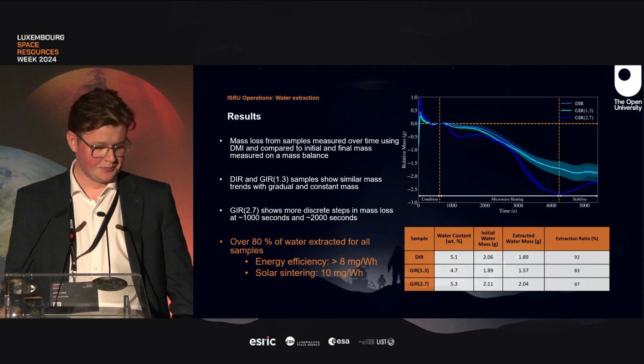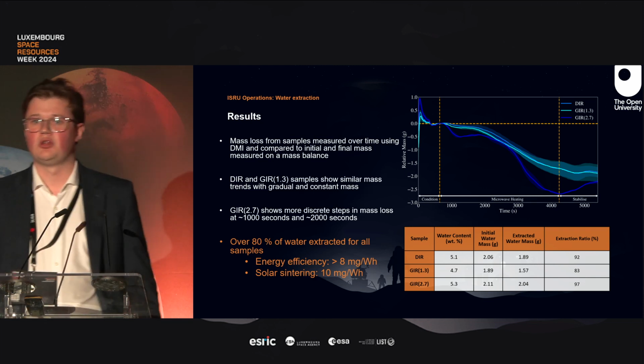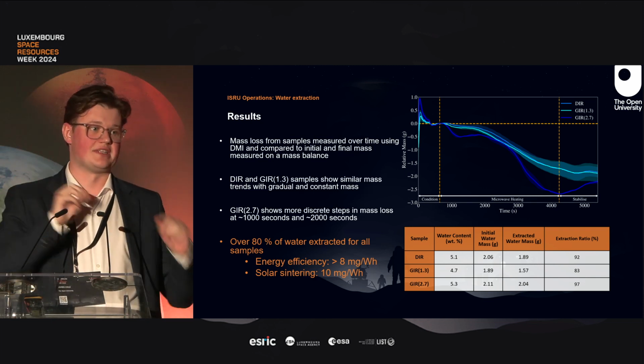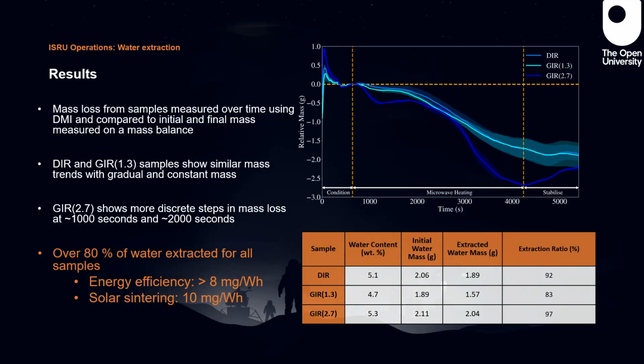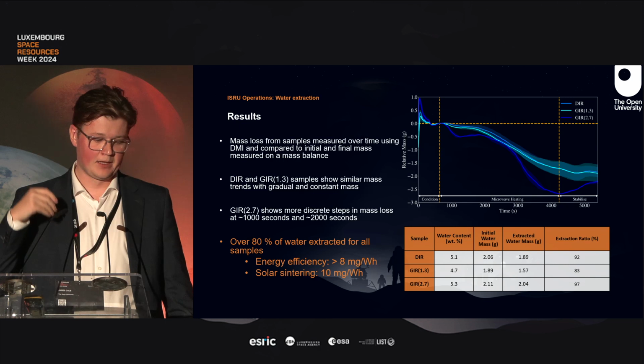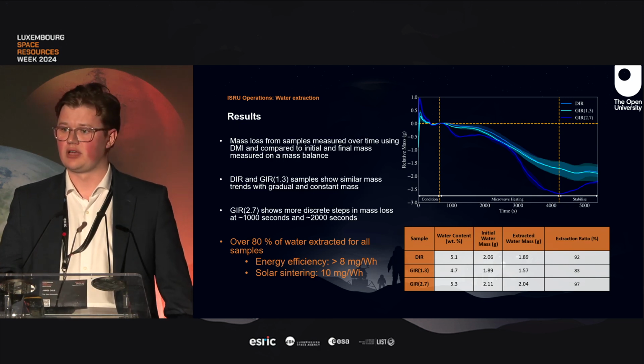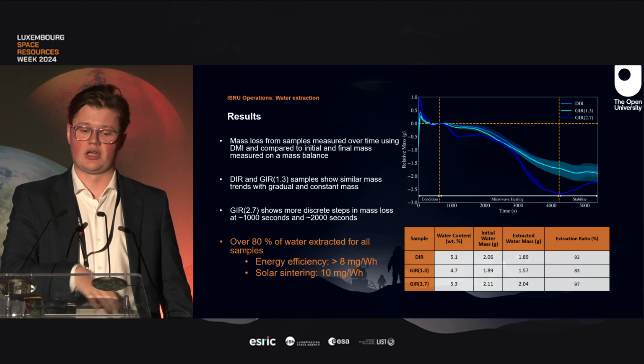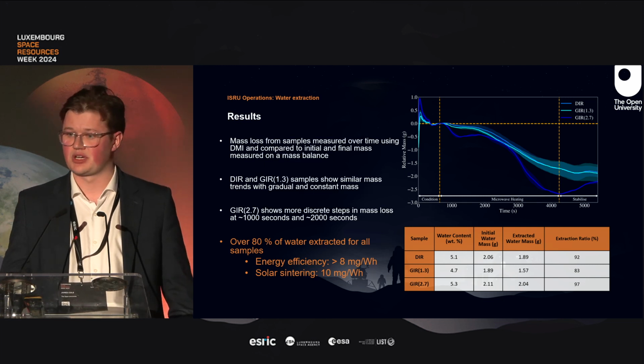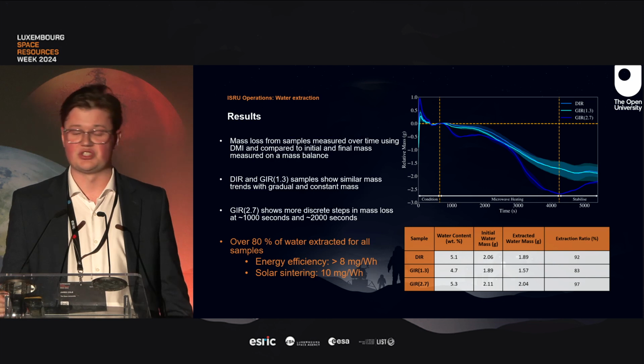before running out. And I think one thing I want to mention about this, although I'm looking into the changes in mass, in detail for all these sample types, the main thing to note is that the microwave's going to extract over 80% of the water in 60 minutes with an energy efficiency of roughly 8 milligrams per watt hour. Now, another paper I've seen puts solar sintering at about 10 milligrams per watt hour. But the thing with microwave heating that might put it over the top compared to solar sintering is that microwave heating only improves with scale, and these are very small samples. So if we could build a bigger system with bigger sample types, then the efficiency should improve from there.